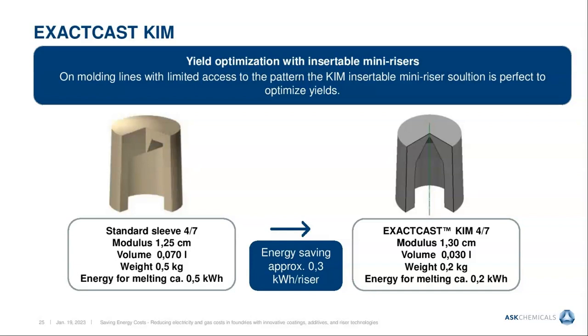This means that we have a thicker wall of exothermic and insulating material that, with less volume of metal inside, we can keep the same module and the same performance. This change of saving kilograms of metal inside of the riser will also give us these energy savings. Approximately when we change from a standard insertable sleeve 4/7 into a KIM 4/7, we can save approximately 0.3 kilowatt-hours per riser.